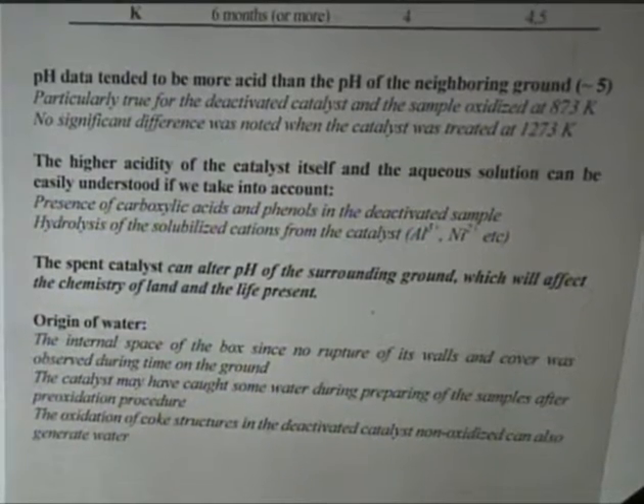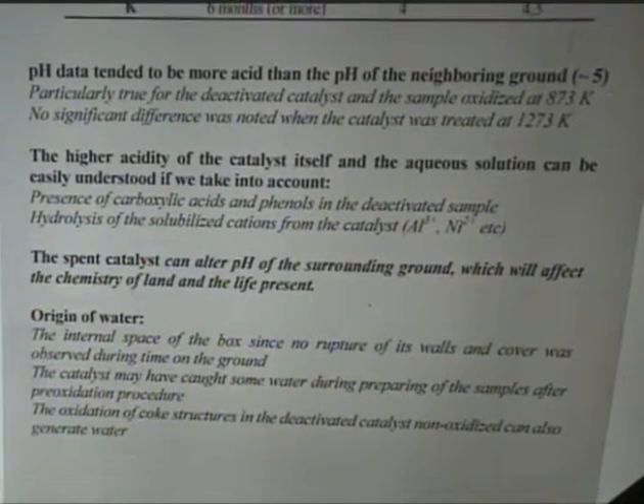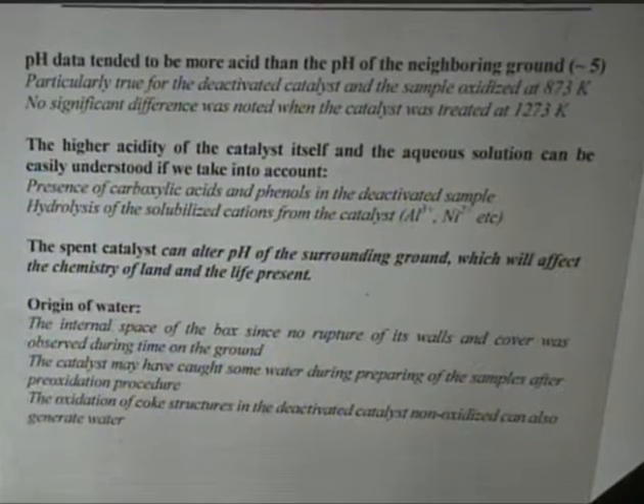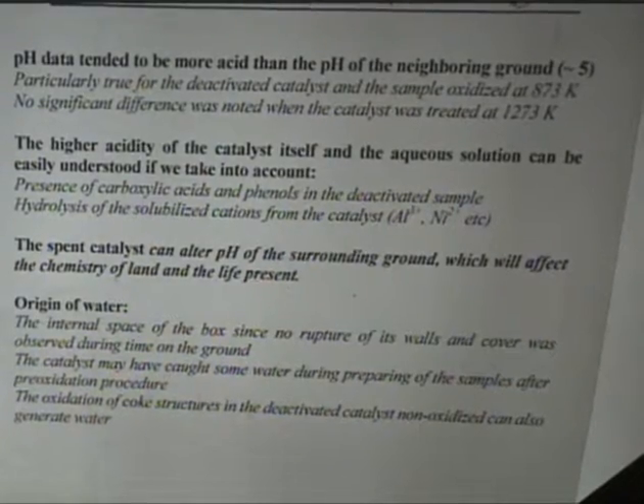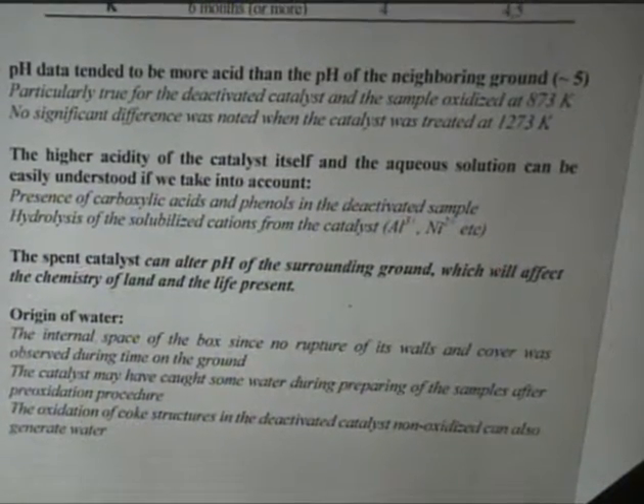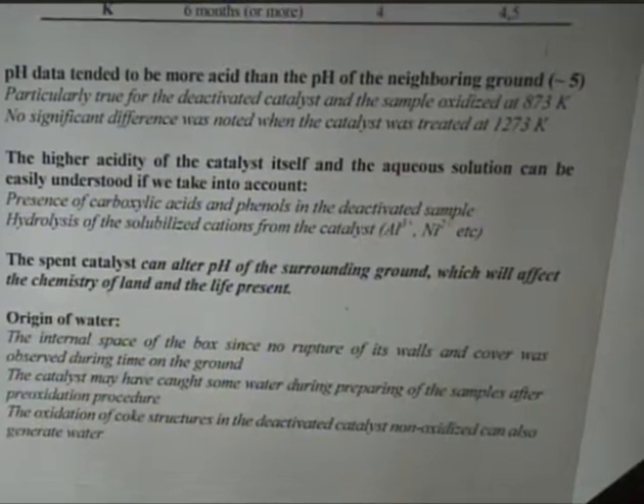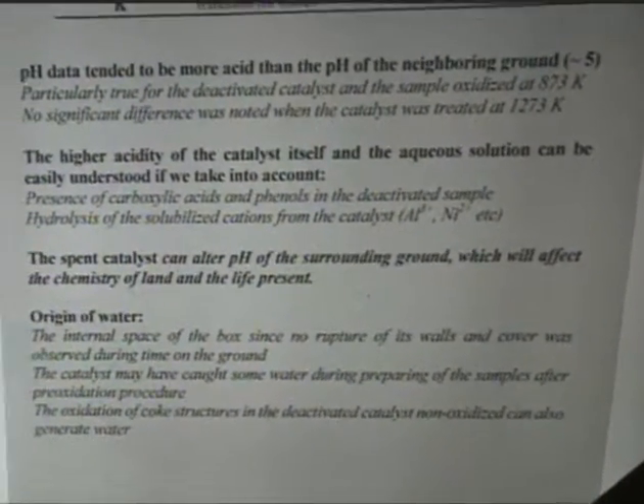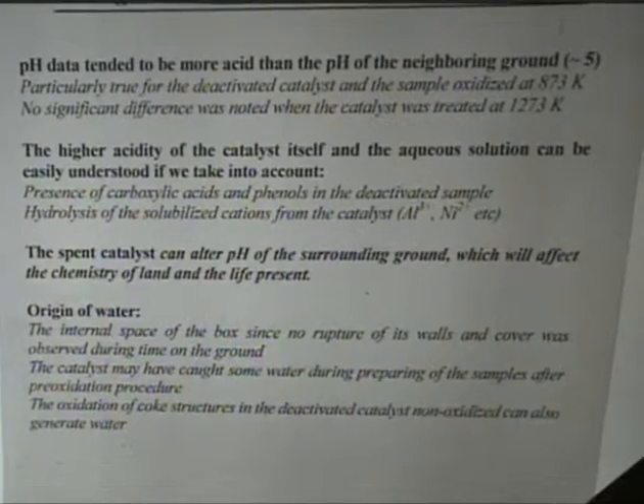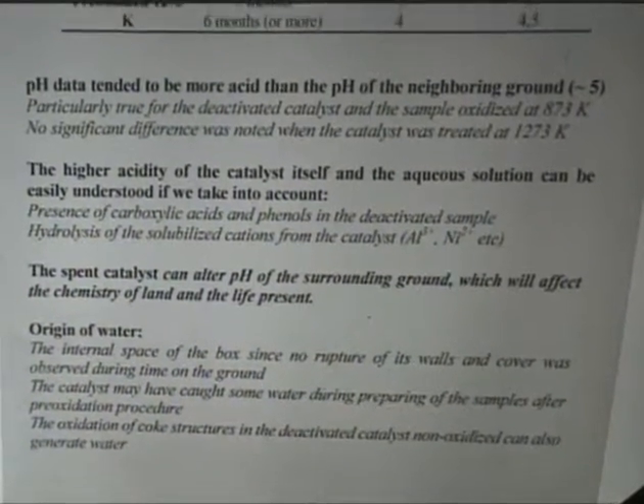As you can see here, an effect of the spent catalyst on the environment, from an environmental point of view, is that the spent catalyst can modify the pH of the surrounding ground, which will affect the chemistry of plant life. And regarding the origin of the water found in the catalyst, there are basically two reasons. The catalyst may have got some water during preparing and handling of the samples after preoxidation, and also in the case of the deactivated catalyst, the oxidation of coke structures along the time may generate water as seen in previous studies.